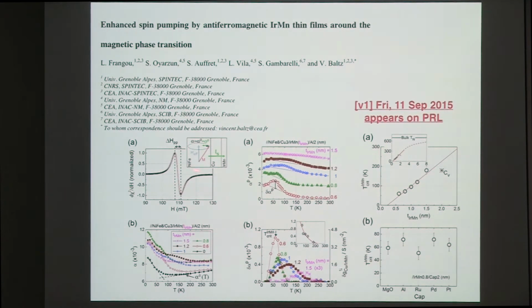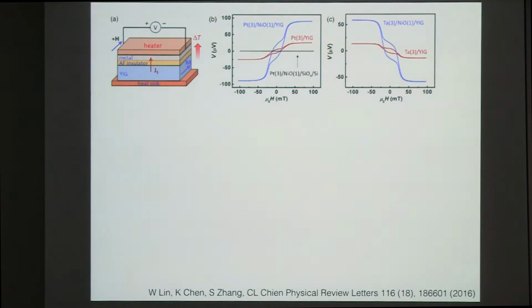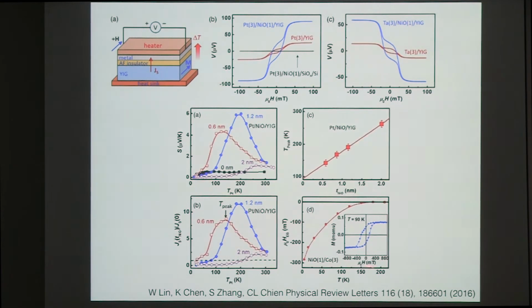So she actually managed to show that if you look at the damping constant, this will tell you how much spin actually has been pumped out of the ferromagnet. And here she used iridium manganese as an antiferromagnet layer, and she also sees some anomalous enhancement of this kind of line width. So actually it is basically the same physics as ours, and also the paper mentioned by Moriyama-san just now, and this kind of spin Seebeck effect. So it's a thermal way of injecting spin. So basically it tells you the same story. But actually I kindly suggest Moriyama-san cite us at the same time as this paper.